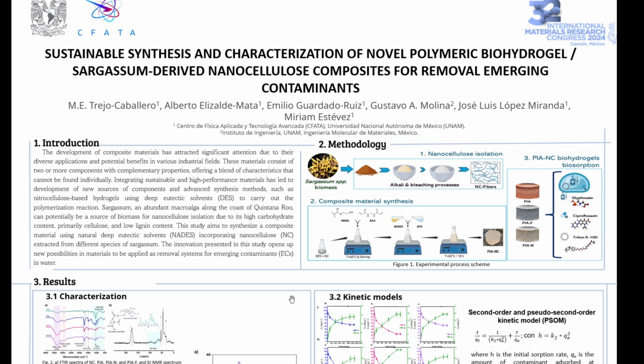Regarding the methodology, the composite material synthesis consists first in the extraction of nanocellulose from sargassum biomass. This was done by physical and chemical processes like alkali and bleaching treatment to obtain it. After that, we proceeded to prepare the deep eutectic solvents, choline chloride glycerol, and the natural deep eutectic solvent, choline chloride itaconic acid, by thermostirring method at 60 degrees Celsius.